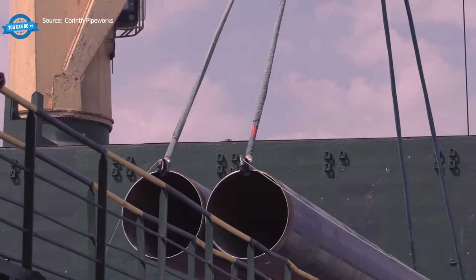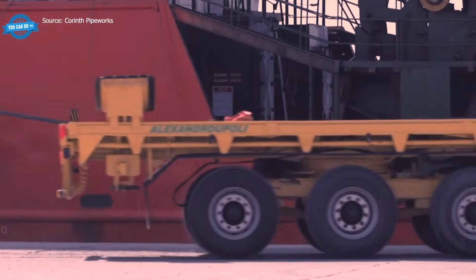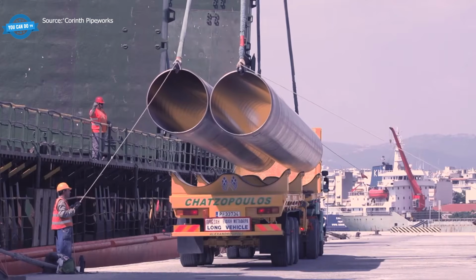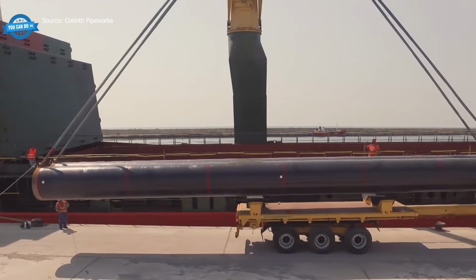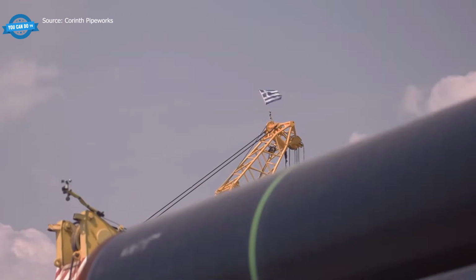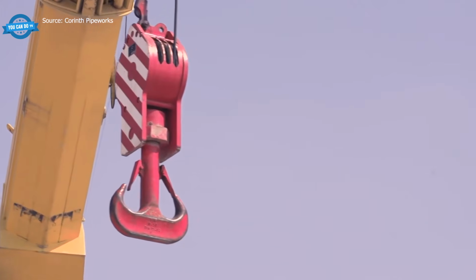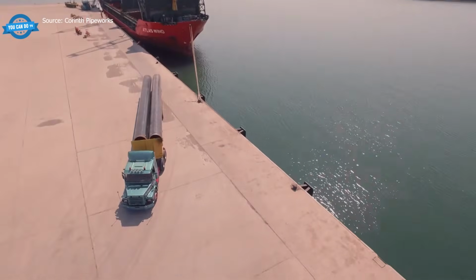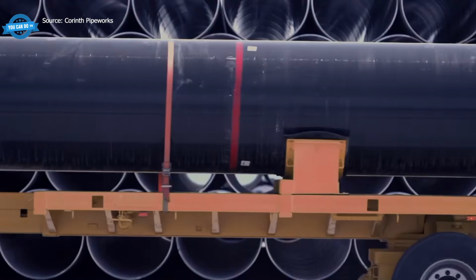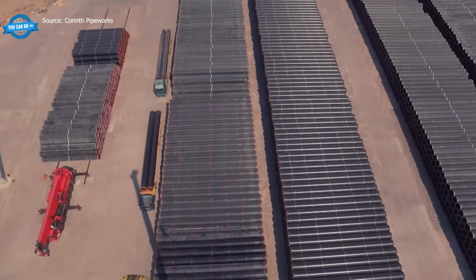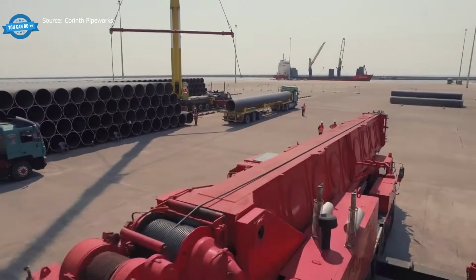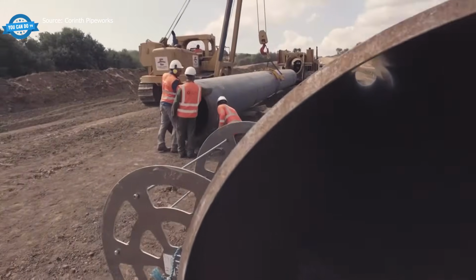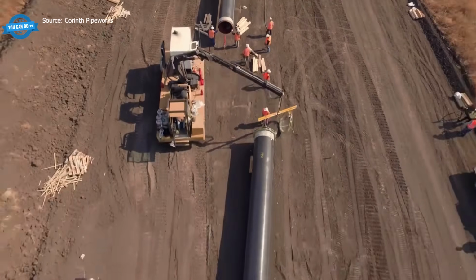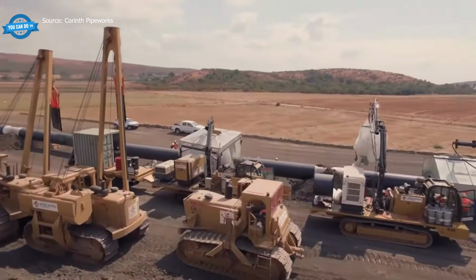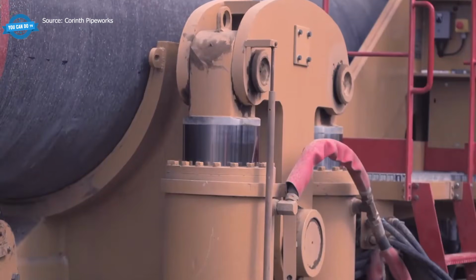This is where coating becomes a problem the offshore industry has to solve at every single joint. A 48-inch pipeline is built from individual pipe sections, each one already coated in the factory. But the coating cannot extend to the very ends of each pipe. Those ends are bare steel, because that is where the next pipe will be welded on. Every weld therefore creates a gap in the anti-corrosion system that the factory cannot fix. The pipeline may look continuous from the outside, but every welded connection interrupts the original protective barrier.